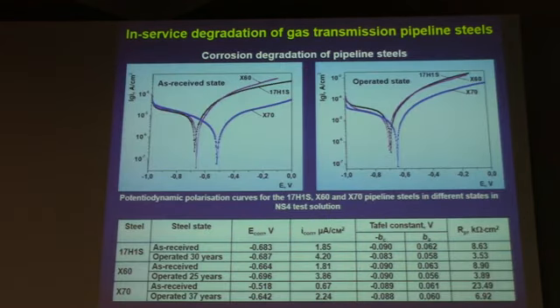Here presented data show polarization curves and the electrochemical properties calculated from these curves for pipeline steels in as-received state and after operation. Corrosion and electrochemical properties were significantly deteriorated due to operation, and electrochemical activation of steels was manifested in an increase of intensity of cathode and anode processes on the degraded steels, and in increasing corrosion current density, in decreasing polarization resistance, and in shift of corrosion potential towards more negative values